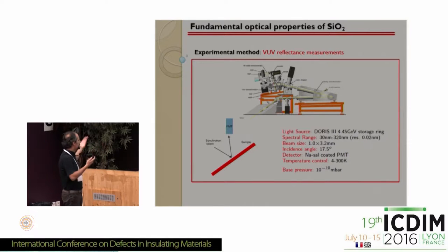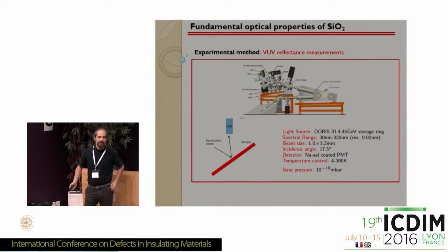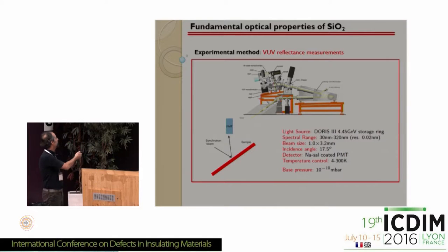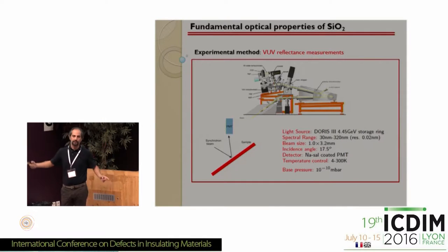So another way, which is quite well known to study this problem, is to do reflectance measurements. This can be conveniently carried out for silicon dioxide by using synchrotron radiation, because it's very broadband and extends to the extreme UV. Here we did a series of experiments where we measured essentially the reflectivity coefficient in near normal geometry by using synchrotron radiation at the DORIS III storage ring, from 5 electron volts to a few tens of electron volts, in order to cover a very wide spectral range.